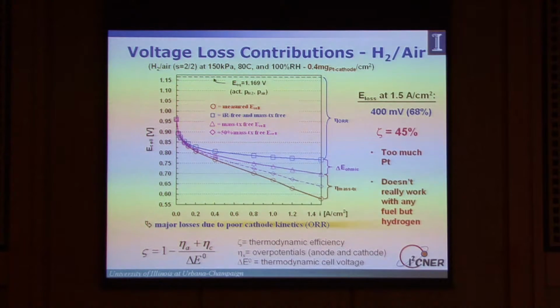Even worse, the platinum shows some degradation processes. It migrates across the fuel cell, depolarizing the cell. It's a total disaster area. Okay, so we have too much platinum. It doesn't really work with any fuel but hydrogen, and the thermodynamic efficiency is not what is advertised. Okay, so what we want to do is step back. We want to understand what the mechanism of this oxygen reduction reaction is. And then we want to use this mechanistic understanding to develop a new catalyst that will solve all of our problems and move us on to greater glory.